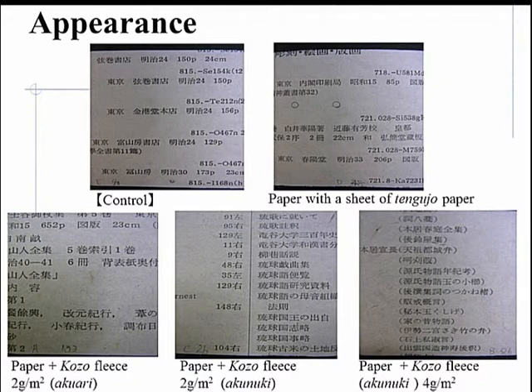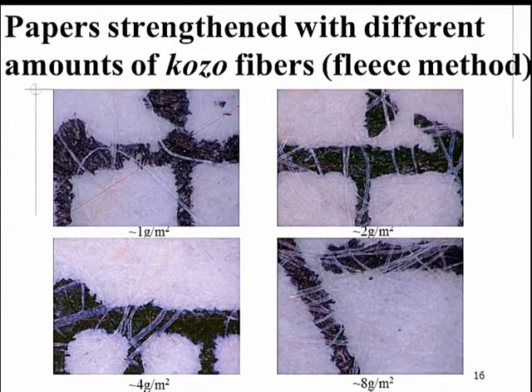Appearance. Visual observation of papers before and after the treatment did not show any difference. Papers strengthened with different amounts of kozo fiber, 1, 2, 4, and 8 grams per square meter, using the fleece method were examined using a microscope. Kozo fibers on the surface of the paper can be seen easily, especially when they are located on writing applied in Chinese ink.